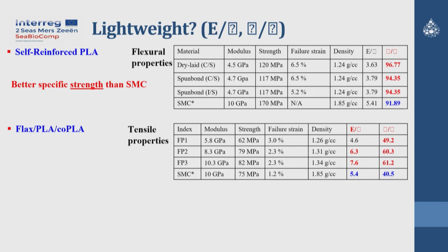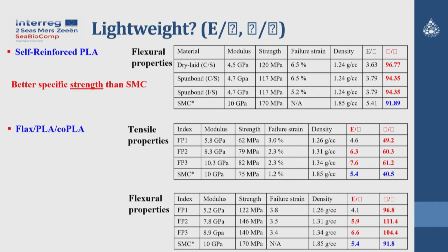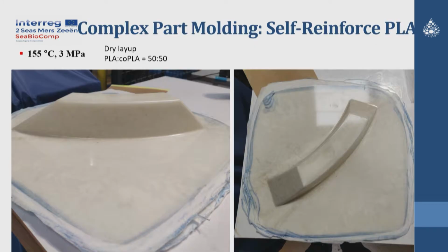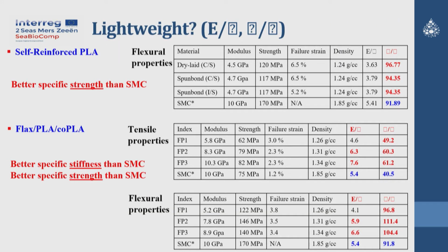And if we take a look at the result of flax PLA and coPLA, you can see that for specific strength and specific stiffness, both tensile and flexural properties, we could greatly increase specific modulus and specific strength. That means if we employ these flax and coPLA materials, we could reduce up to 50% of structural weight compared with conventional SMC. So this is a really big advantage. We can use bio-based composite, we can reduce the carbon footprint, and we can decrease the structural weight.